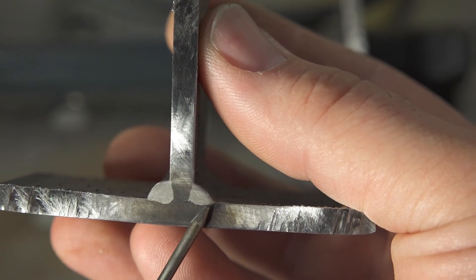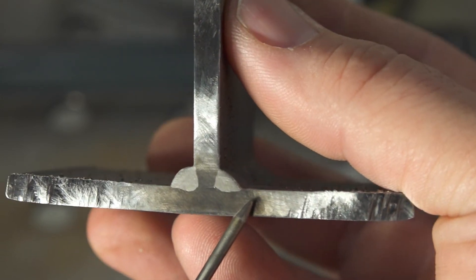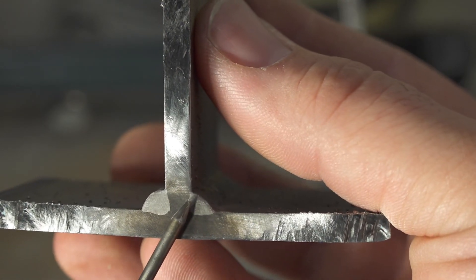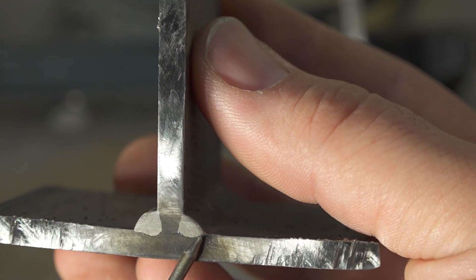And you can see in both cases I got pretty decent penetration. Again this was the welder turned down a little bit, not super deep penetration but it is tied in all the way along and even all the way right to the toe on both sections, it is tied in right to the toes.